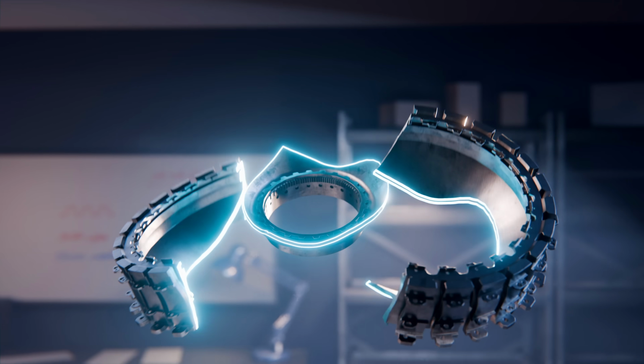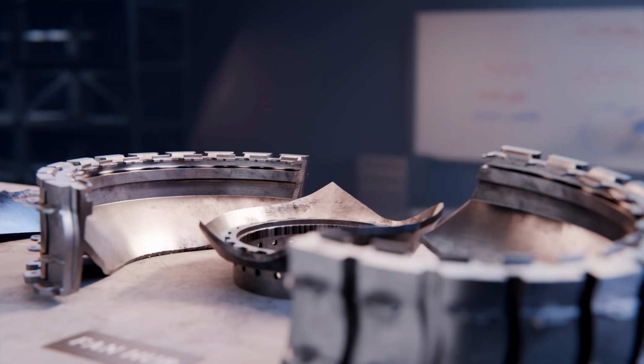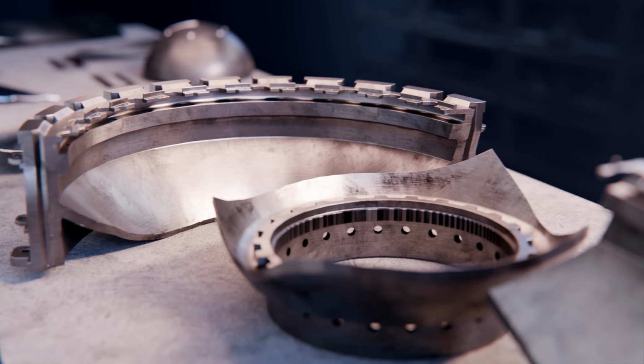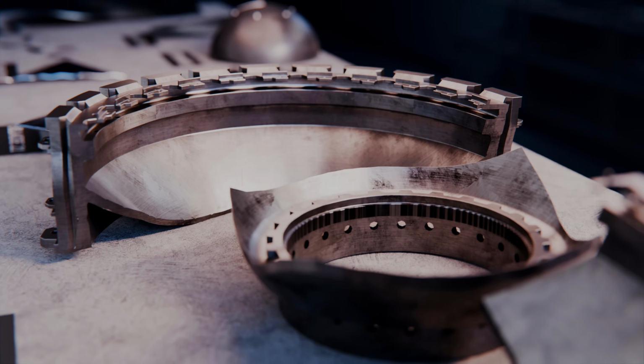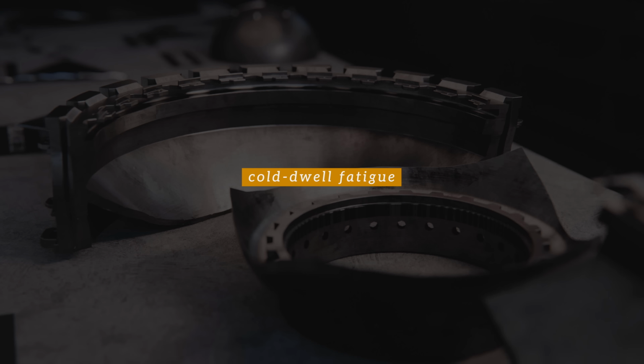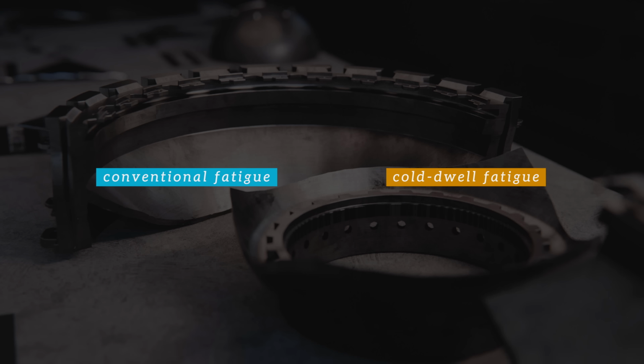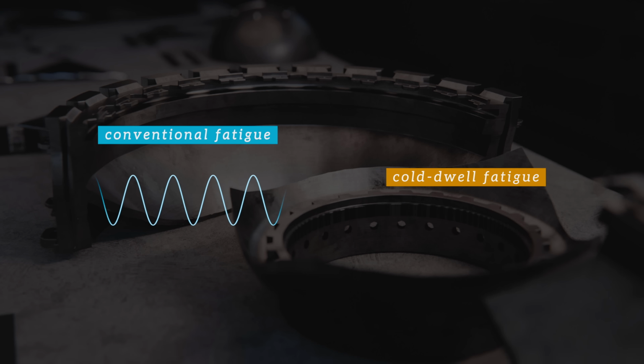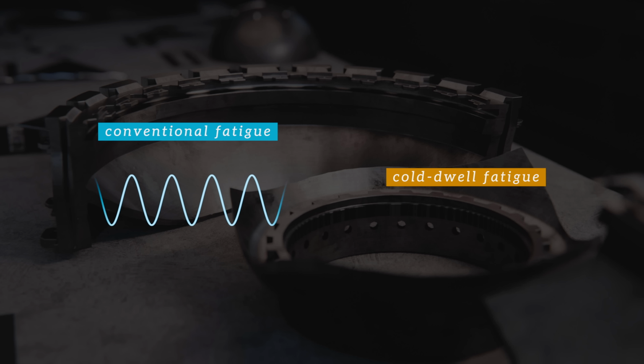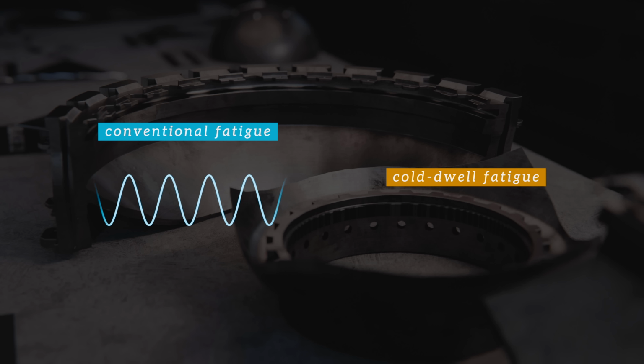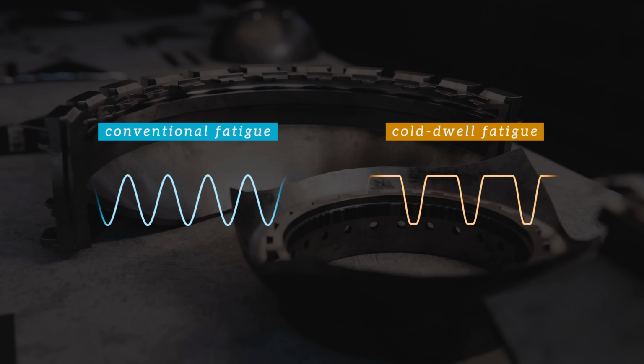The real cause was a hidden weakness in titanium alloys, their susceptibility to a unique failure mechanism called cold dwell fatigue. Unlike conventional fatigue, which occurs when a component is subjected to cyclic loading, allowing cracks to grow incrementally with each stress reversal, cold dwell fatigue occurs when cyclic loading includes a sustained hold at high stress.